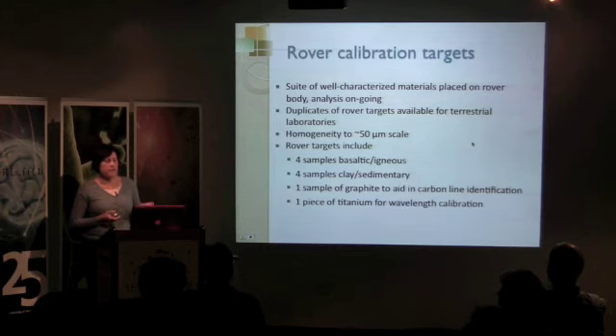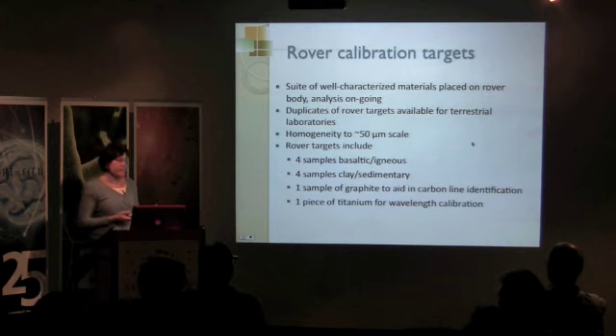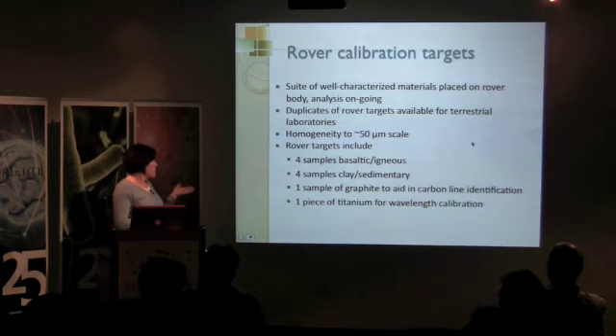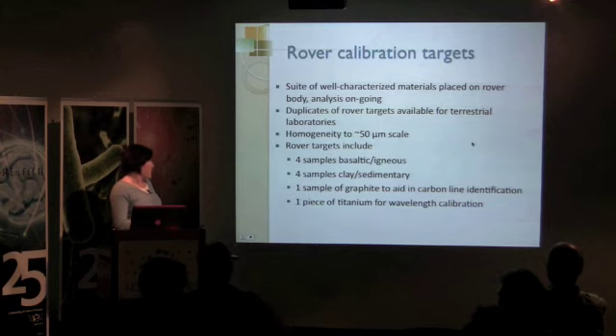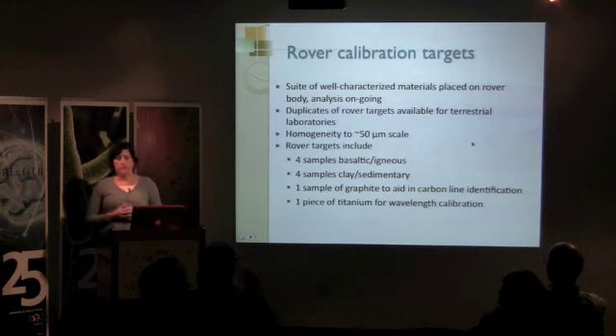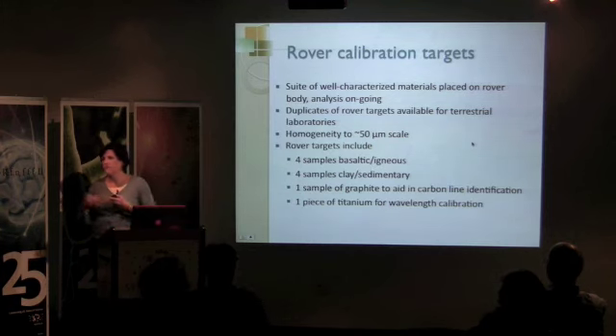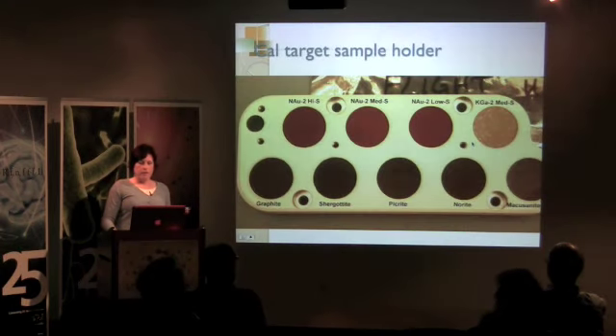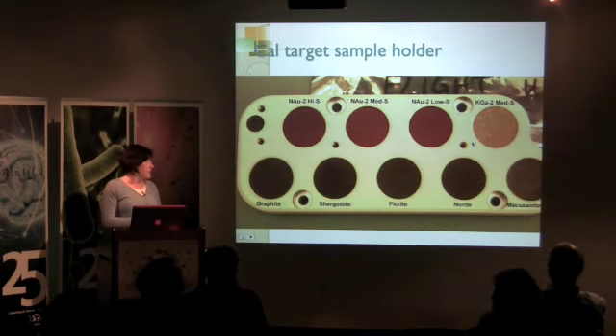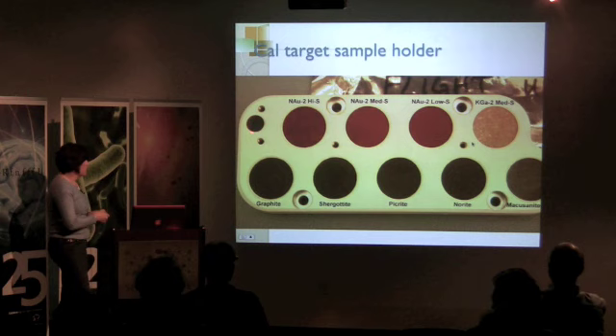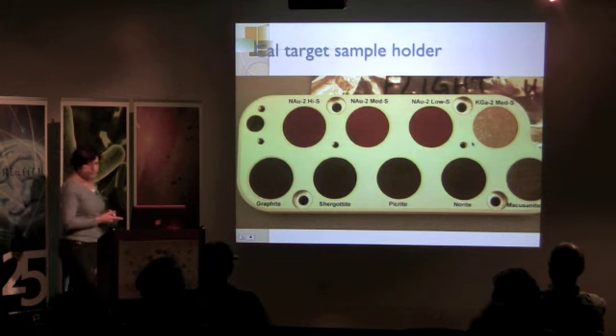Sorry, nine samples plus a piece of metal. So there are 4 samples that are basaltic igneous composition, 4 samples that are sedimentological, and there's 1 sample of graphite to aid for carbon line identification, and then there's also a piece of titanium metal just to do a sort of standardization or wavelength calibration if that's needed. And here's the target sample holder. The metal titanium piece would be in there.